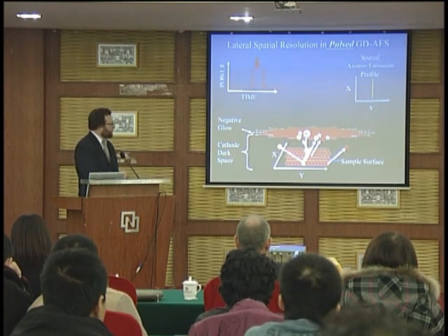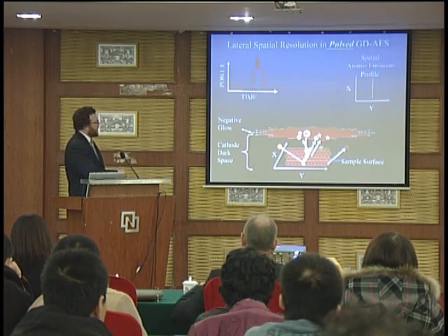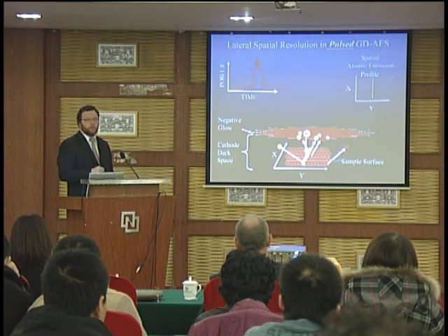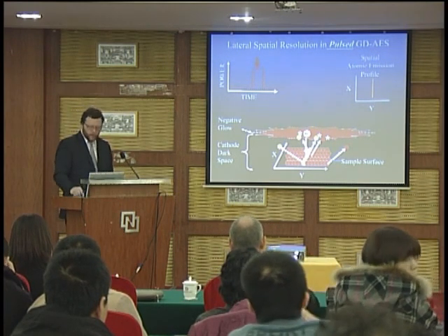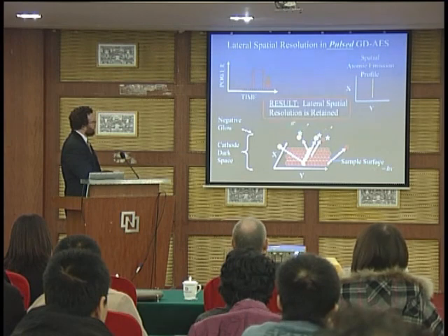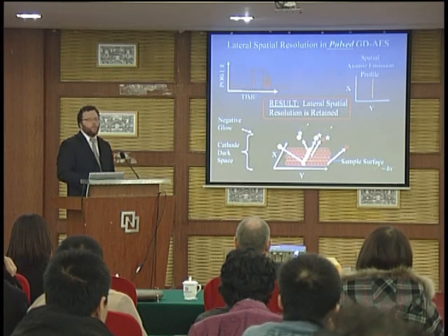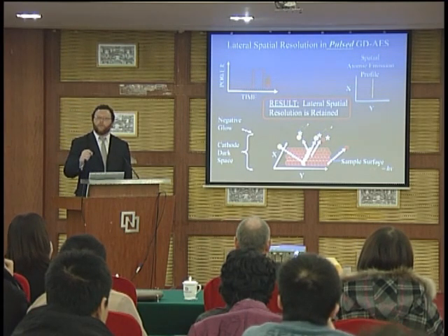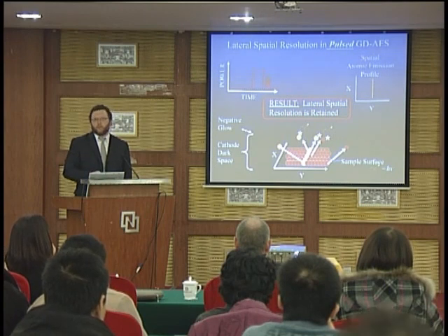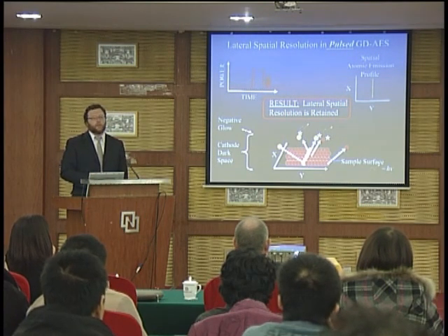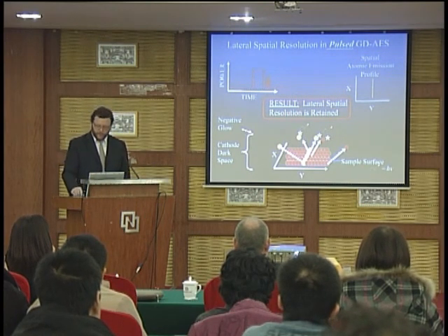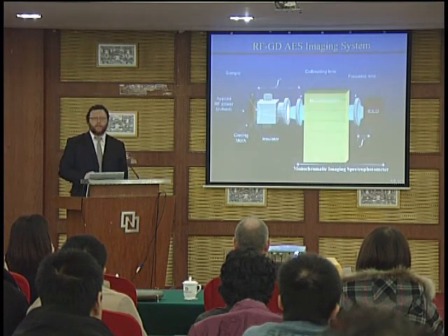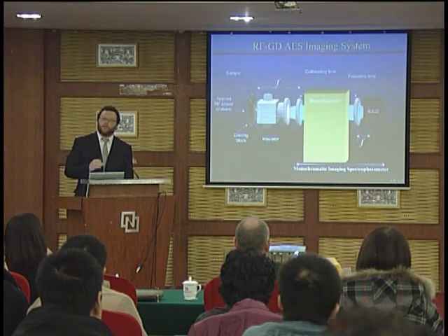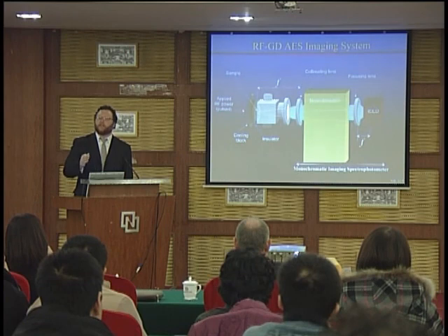And so what we do then is simply excite those atoms that have moved directly from the sample surface and are excited by the negative glow, and turn the discharge off. And the only thing that remains are the ones that moved a small distance from their origin. And therefore we get this high spatial resolution, on the order of, say, 1 millimeter to 100 microns. Now to do that, you need some means of doing some spatially selective, wavelength selective spectroscopy.